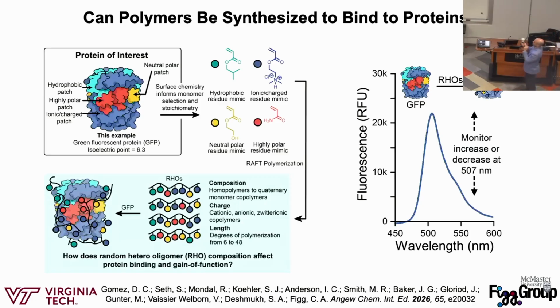So after a lot of trial and error, we came to these 4 monomers in this first paper, where we're using a hydrophobic monomer for the hydrophobic patches, a cationic charge monomer for the anionic charge on the surface, a neutral polar monomer for solubility and also some hydrogen bonding, and then just an acrylic monomer for hydrogen bonding. And the idea is if we can do a RAFT polymerization, so essentially mix the monomers, bubble some argon through it, run the polymerization, you can get grams of material.